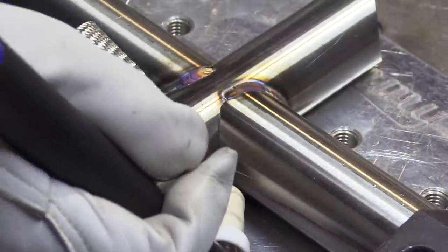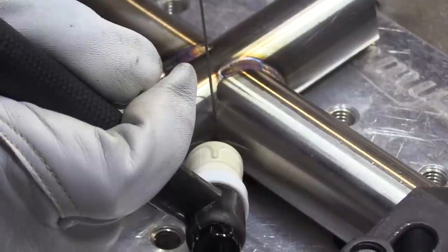Let's take another look at one. When I light up, let's count how long it takes me to get moving, to dab rod in there and get moving. Thousand, one thousand, there goes the rod right in there. So I hit it at 120 amps. And then after about three dabs or so, I back off the pedal a little bit, probably to about 90 amps or so. I don't know. I wasn't looking at the machine.